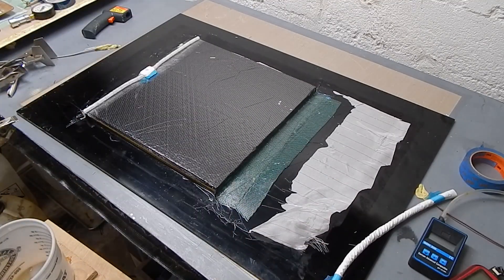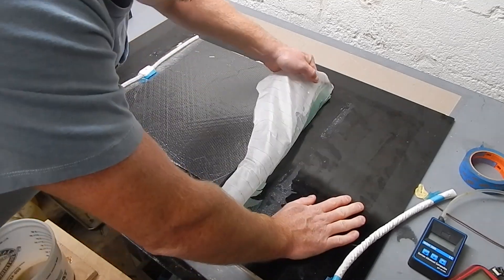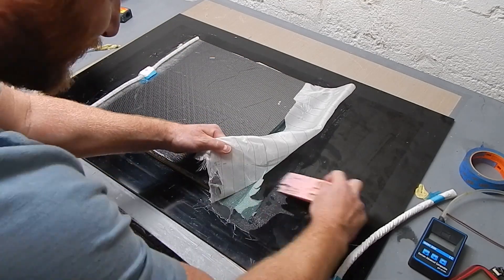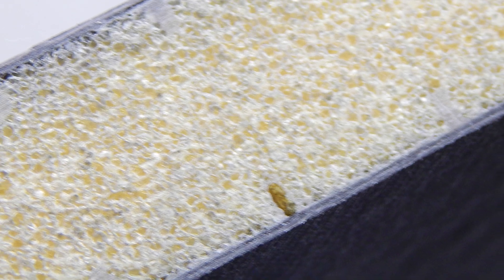And there's the finished panel, it looks nice and solid. Pretty well stuck. I had to get a wedge under there, popped off, and it looked pretty nice. There was a little bit of air in the surface on the mold side. You could see from the spray adhesive that sprayed on really nasty, some obvious blemishes there. And there was definitely a little bit of air on the bag side bond line. You can see some of the core grooves not filled, which is not ideal.